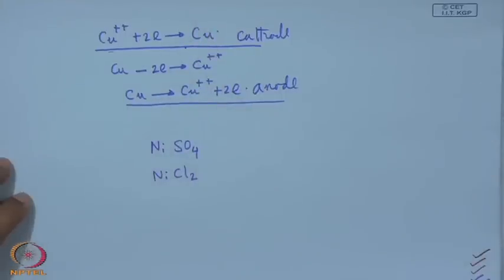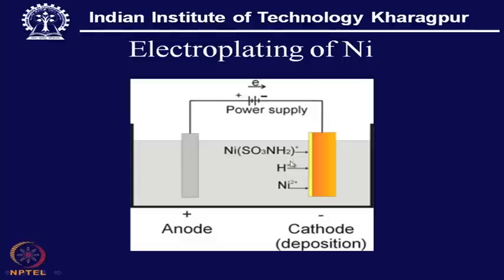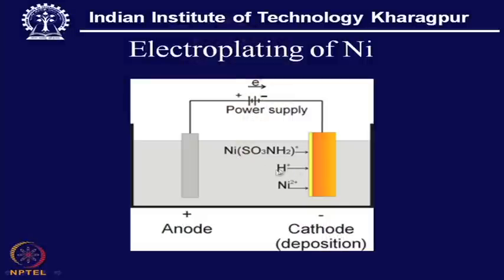Now, one thing we cannot ignore is that we have here H2O, and that will be split into hydroxyl ion which is negative, and hydrogen ion which will be positive. Now, this hydrogen can create some kind of problem in the coating of nickel. The reason is as follows. If we see this illustration, along with this nickel ion, hydrogen will also be collected here, and this hydrogen can be trapped at this point. So, there we must have sufficient arrangement, a good wetting agent, so that this hydrogen can be removed, and this wetting agent will create a surface for immediate adsorption of nickel ion and not the hydrogen ion.